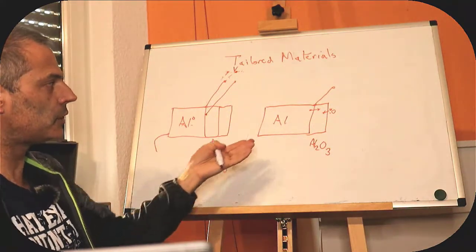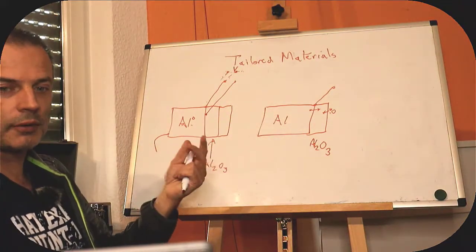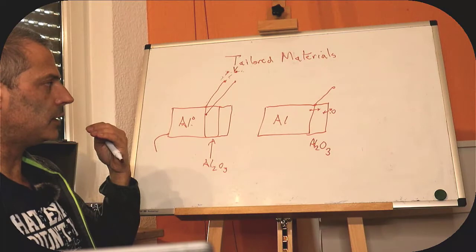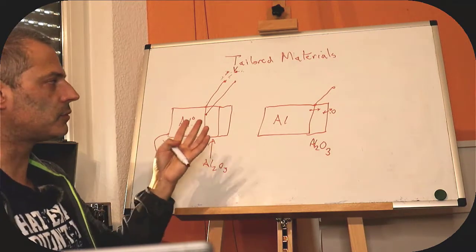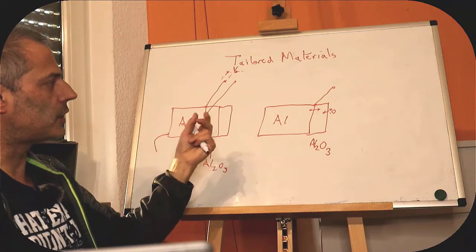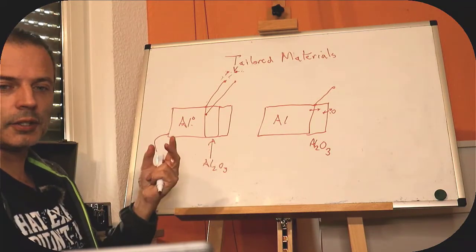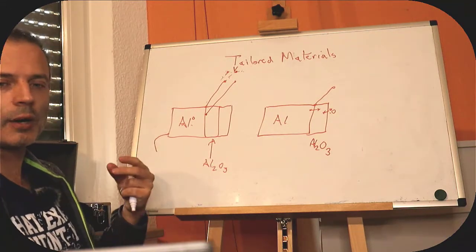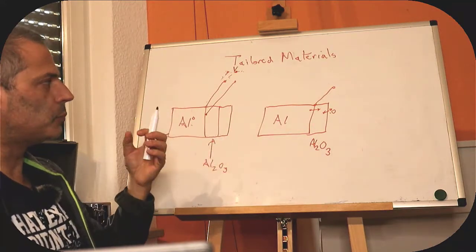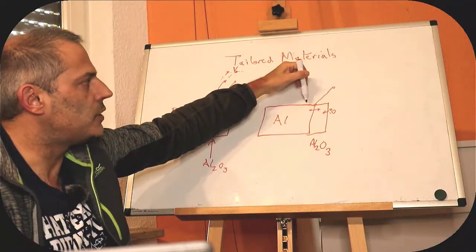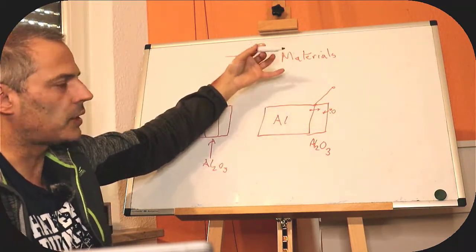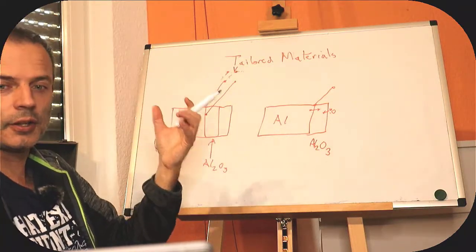If we take something like aluminum oxide, the conductivity of the layer will also go up. And so we will have two effects which will both combine to make a thicker layer. So if we take a piece of iron and we heat it up, it changes color. And the color change is due to the thickness of the oxide layer. And the thickness of the oxide layer is effectively a record of how hot the material got, because for the same reason as here, we reach very rapidly a position where the gradient of this change of voltage is not enough to force these atoms to move anymore. So we end up with a relatively fixed thickness of oxide.